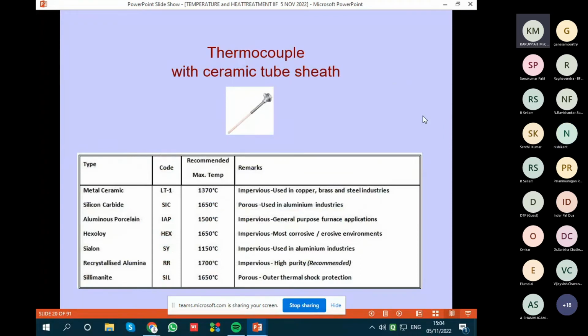If you are using ceramic thermocouples for higher temperatures, say 1300, 1400, 1500, in rolling mills or such applications or forging, then these ceramic sheaths are used. Or even this thermocouple is used in your chemical laboratory for stirring apparatus, where the temperature is measured. The stirring apparatus has got a platinum thermocouple. They use the ceramic tube.